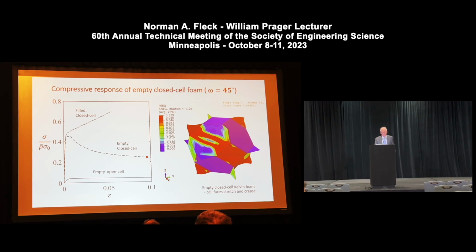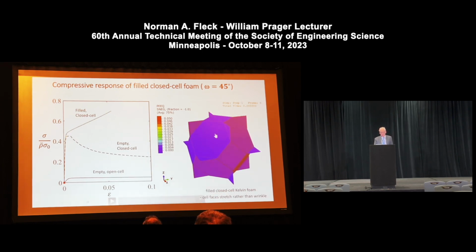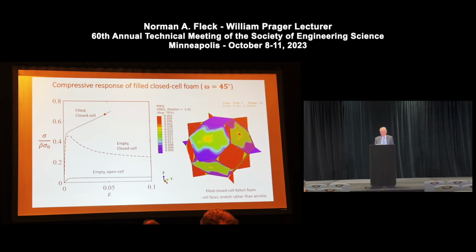Now I take the case of a filled closed cell foam. So here's the foam. I'm going to fill it with, think of it as water, something which is incompressible, the volume is constant, and now when we load it up, we observe the cell edges will still want to deform, if you follow the Gibson-Ashby argument, in a bending type manner, but the cell faces will stretch. The early response is similar to that of the empty closed cell foam, but what's very different is the subsequent strain hardening. So this is a highly stable response, and again, it's a geometric hardening, and the consequence will be, if you think of the large lattice, that you get a stable macroscopic response without forming crush bands.